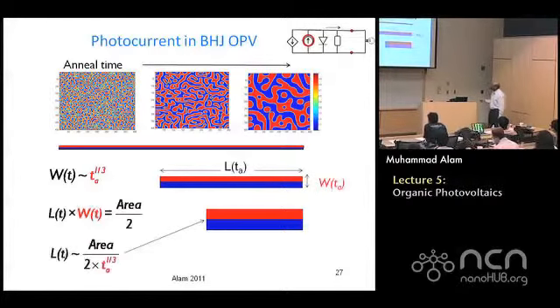So now think about it. What is the interfacial area of this complicated structure? You know the original area, divided by 2, because blue and red was 1 to 1. So area divided by 2. W, this width, evolved as a function of anneal time as t to the power 1/3. So without doing anything else, despite the complexity of the structure, you can immediately find out how the interfacial area of this one will evolve as a function of anneal time. You don't have to do anything else. Now, how does it help me? I can calculate the exciton current based on this in the following way.